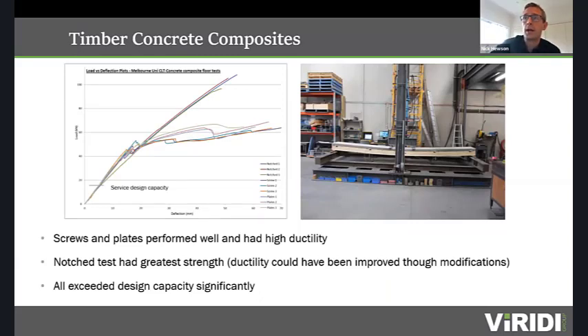The screws and plates had very, very high ductility, with significant reserve strength after the failure of the composite connection. The notch test had an astonishing amount of strength and performance, but a slightly less ductile failure, which is something we would propose to improve through further testing if the floor had gone ahead. But all of them significantly exceeded the service design capacity of the floor. So this was my first experience of TCC floors, and what was clear to me was that they actually worked incredibly well, and they really harnessed the benefit and performance of both materials.